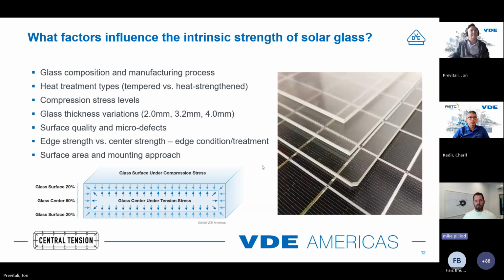Within the solar industry, there's 2 millimeter, 3.2, 4 millimeter. Obviously it's a continuum. If you can make those, you can make thicker or thinner ones that are out there. Within the architectural, it tends to be 5 millimeter and up. So solar is driving to thinner thicknesses relative to architectural, hence maybe the industrialization process of things. Within the architectural, you tend to be a bit thicker than in solar.